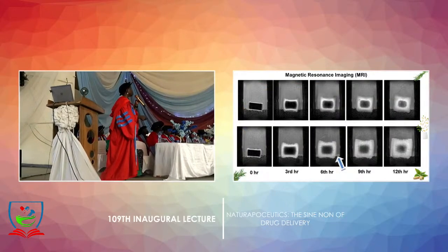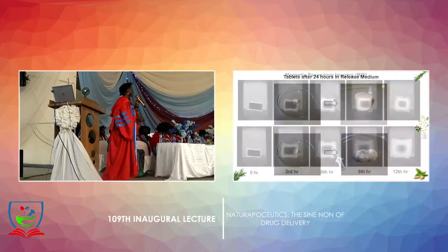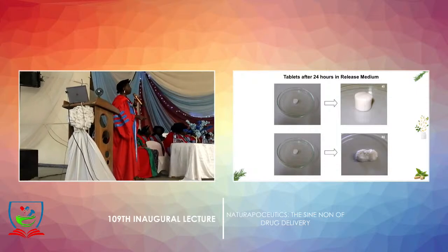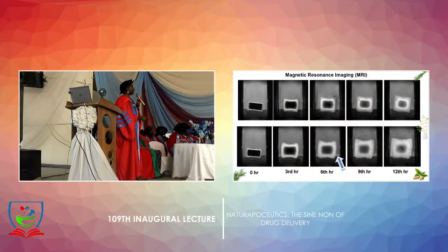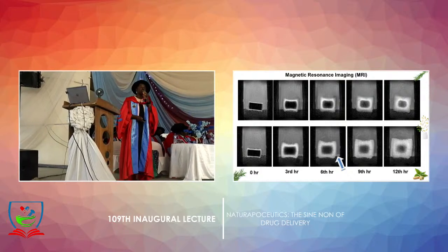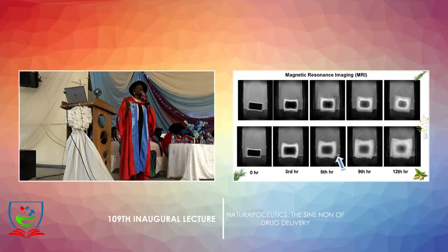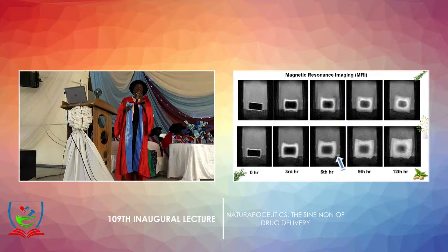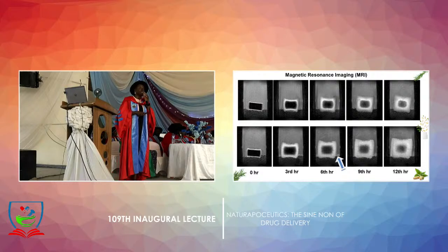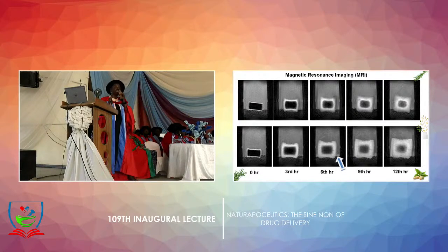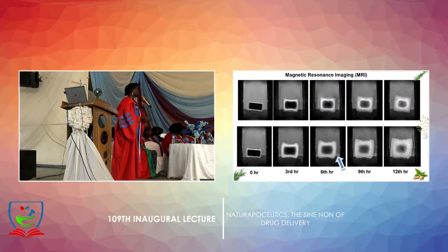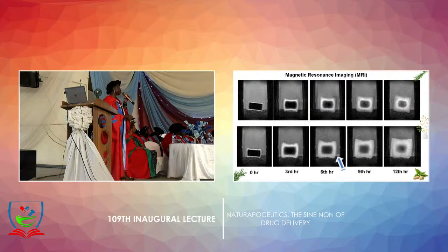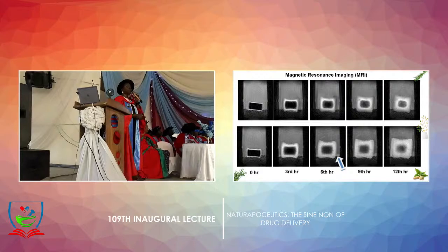When we did that, we were able to find out that yes, this is pH 1.5. It stayed there. When you look at this, you will see that the material looks this way, and you can see some particles dropping off there. That confirms that we're experiencing surface erosion. The particles are chipping off. Remember, we said it's a pH responsive material. At pH 1.5, it retains its shape. At pH 4.5, it loses its shape. This is what happened. This is pH 4.5. This is pH 1.5.